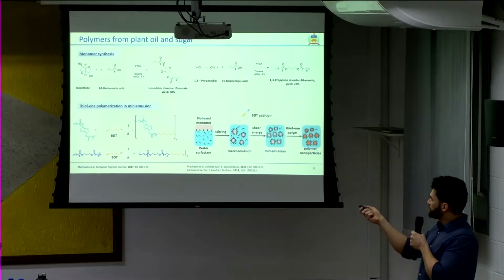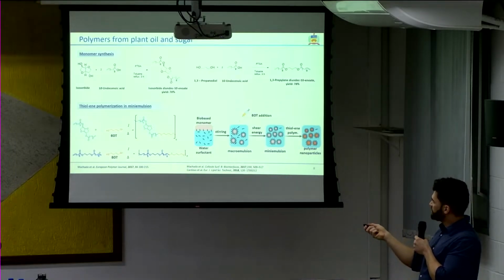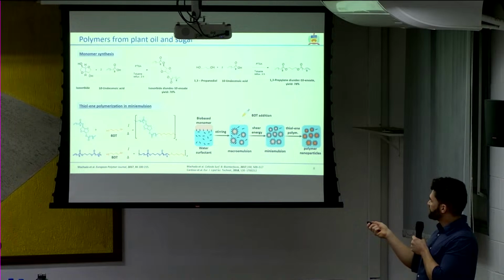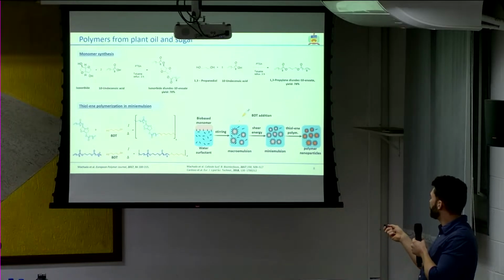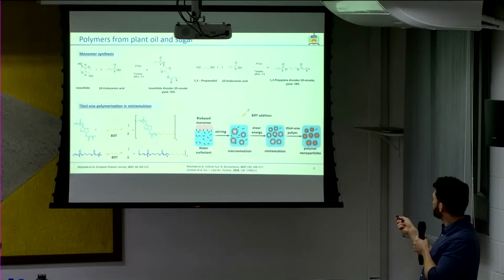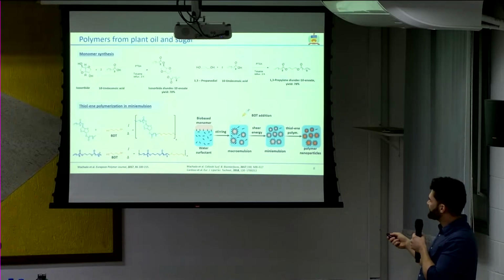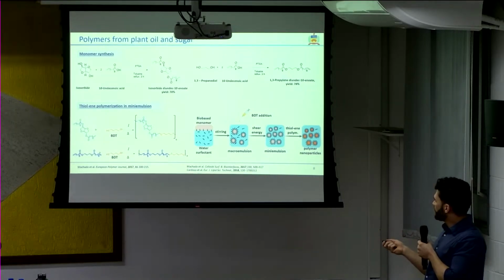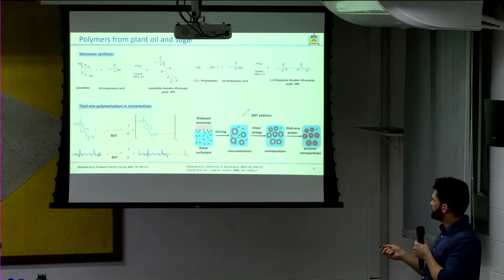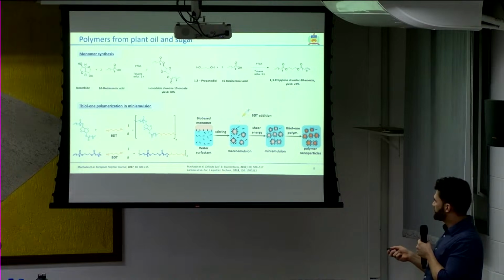So the monomer synthesis step is very easy. It's just the Fischer esterification of the alcohol with the carboxylic acids using PTSA as catalyst for isosorbide and propanediol. So here we have the diene monomers, or alpha-omega diene monomers, because we have the double bonds at the end of a very long fatty acid chain. And then the polymerization step is the thiol-ene polymerization, so it's co-polymerized with dithiol.